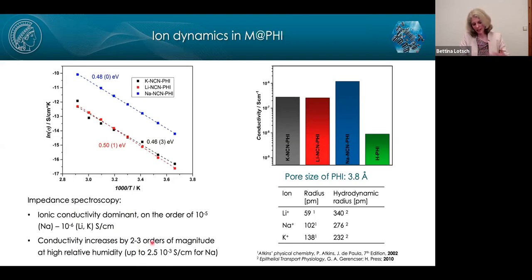As we ramp up the humidity, the conductivity goes up, actually up to roughly 10 to the minus 3 Siemens per centimeter. And we believe that these differences in conductivity that we see, with the highest conductivity observed for the sodium compound, really correlate with the hydrodynamic radius of the system combined with the stacking polytype in these systems, which is actually different for the different alkali metal ions.